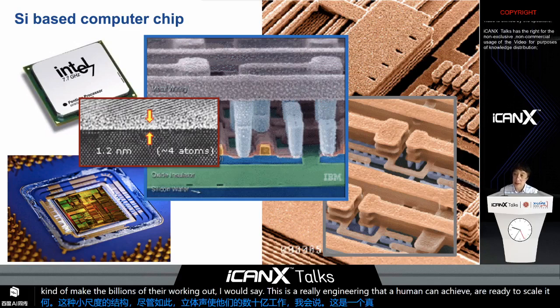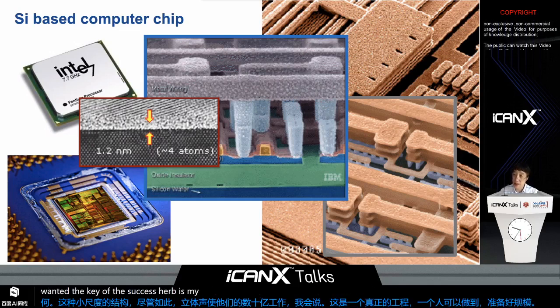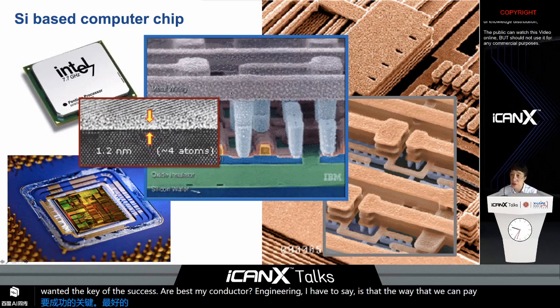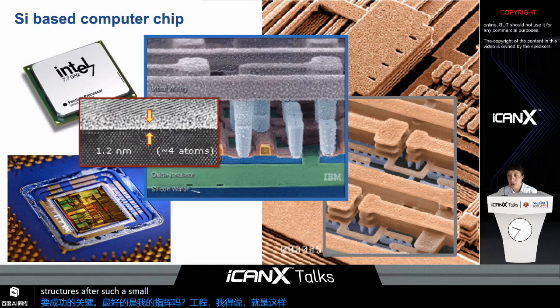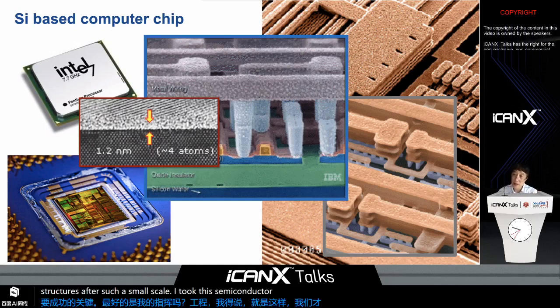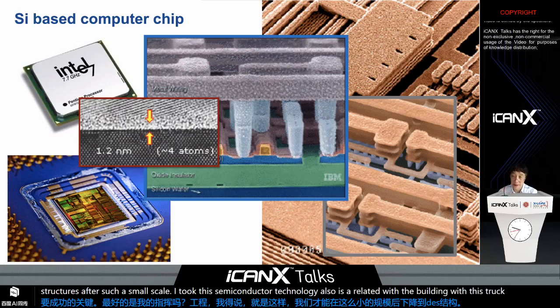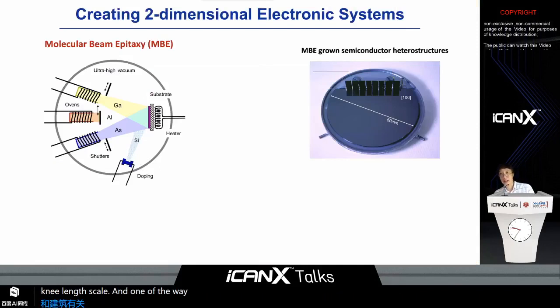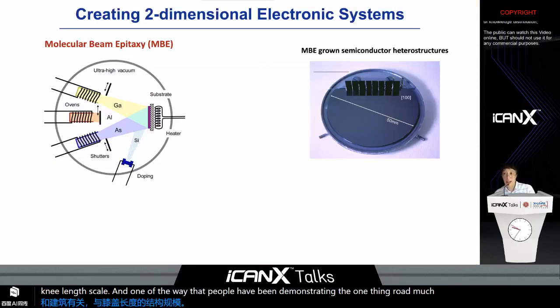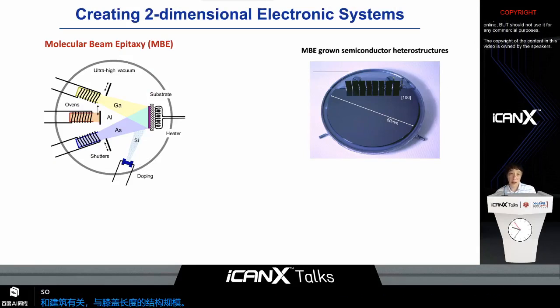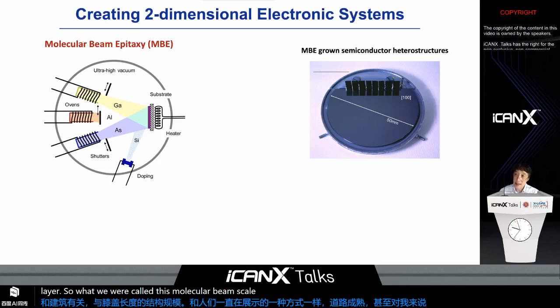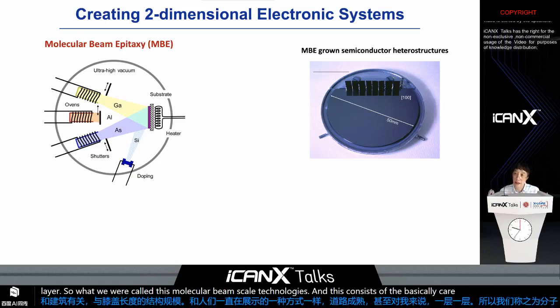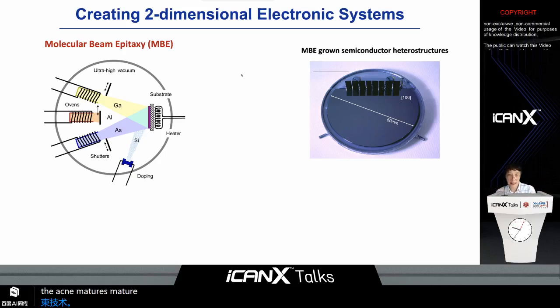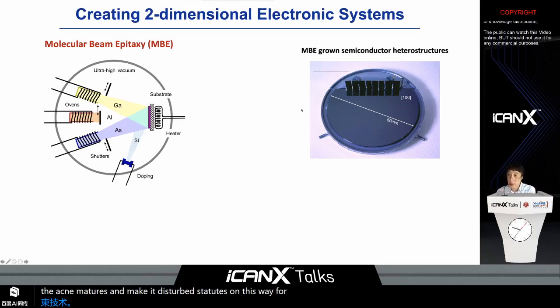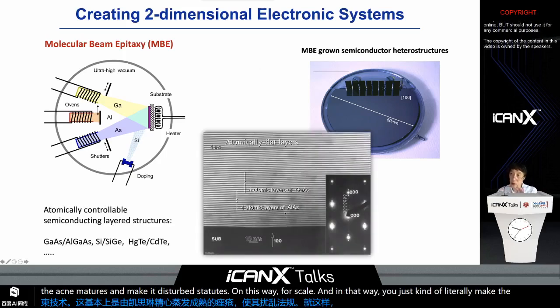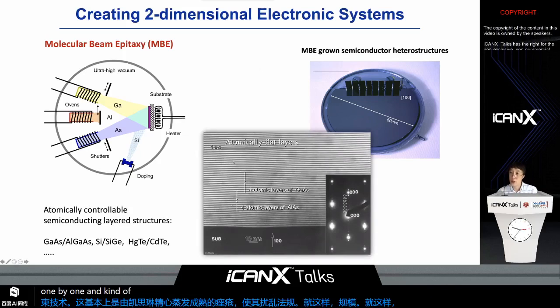One of the keys to the success of semiconductor engineering, I would say, is the way that we can tame structures down to such a small length scale. Part of semiconductor technology also involves dealing with structures at the atomic length scale. And one of the ways people have demonstrated this is that one can grow material just atomic layer by layer, which we often call molecular beam epitaxy technology. This consists of careful evaporation of atomic materials and stacking them onto the wafer. In that way, you literally make the atomic layers one by one, and stack together the compositions that you want.